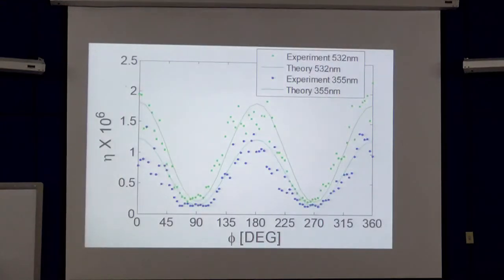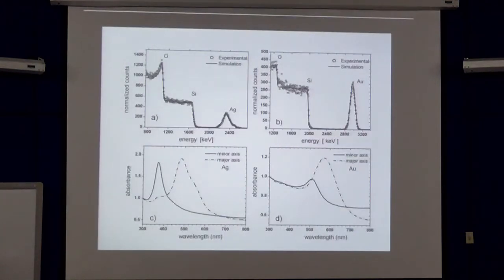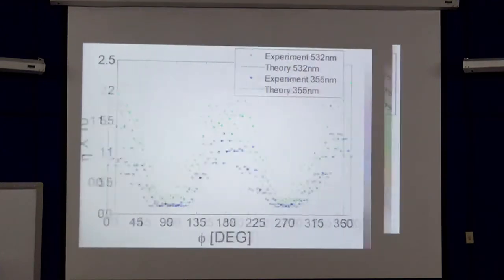Well, these are some experiments related to wave mixing. Just to compare, the experiment in ultraviolet with the green, it corresponds to silver, and the difference is related to the absorbance spectra, because when you test the sample with ultraviolet, the absorbance is big and the refraction is small. When you test far from resonance, the nonlinear refraction increases and the absorbance decreases, as you can see. It can be deduced from the spectrum.